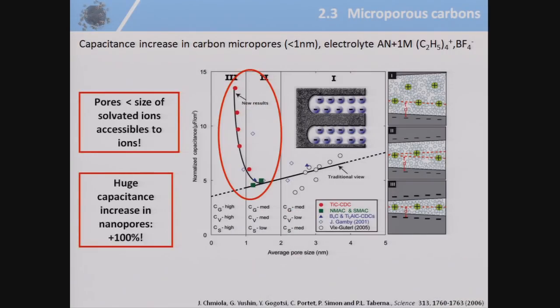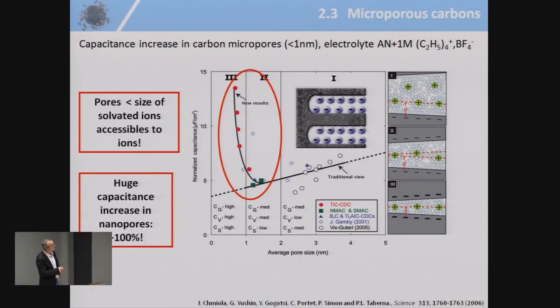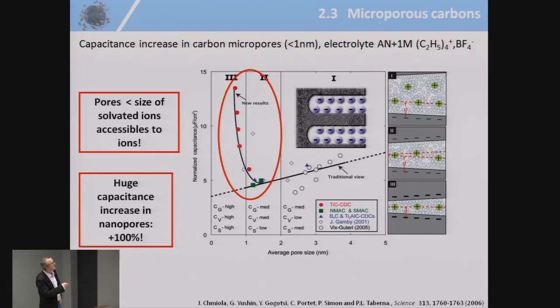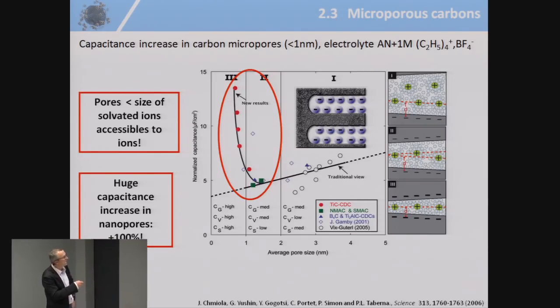And we end up with a method, I'm not going into detail about that, but with a colleague, we were able to produce carbons with a controlled pore size below 1 nanometer. And what we have found here, we have found with our materials, this is a carbon pore size, this is the normalized capacitance of carbons.